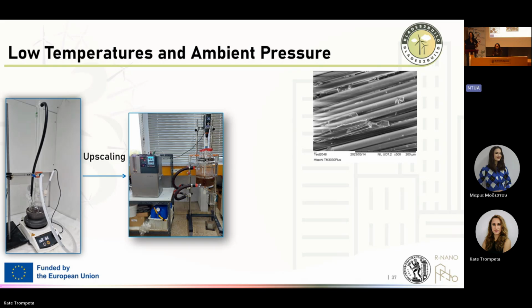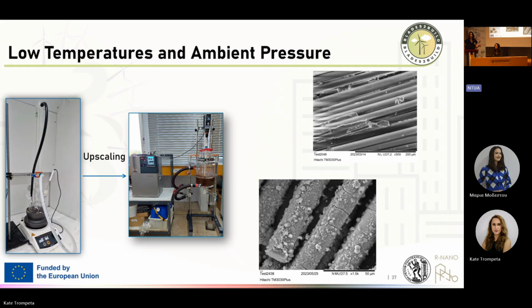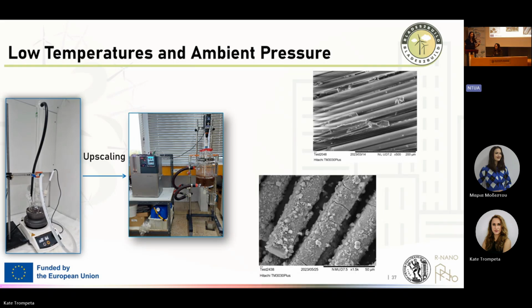However, as you can see, we had some fibers that were not cleaned properly, and we had to use more catalyst in order to clean the fibers. And then when we used more catalyst, we had problems with our fibers because the catalyst not only penetrated the resins but also degraded the fibers due to the alkali environment that we used.